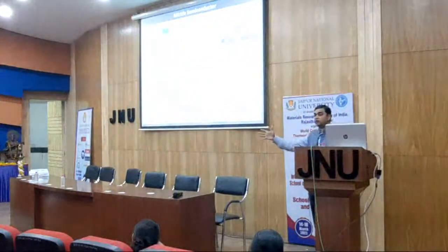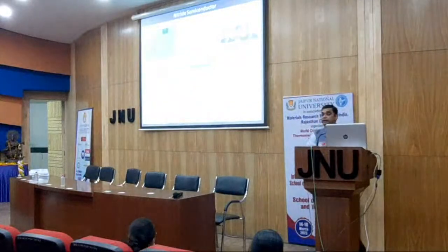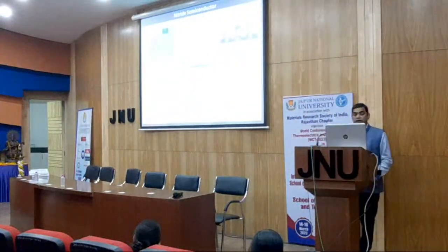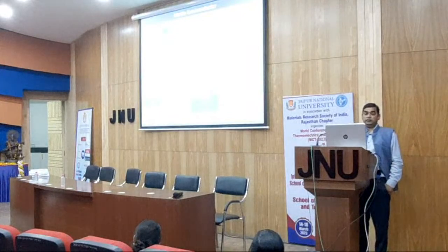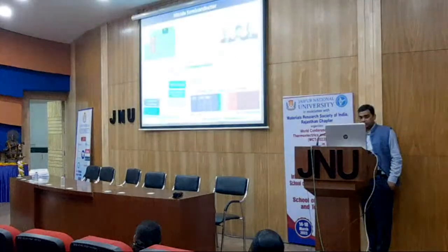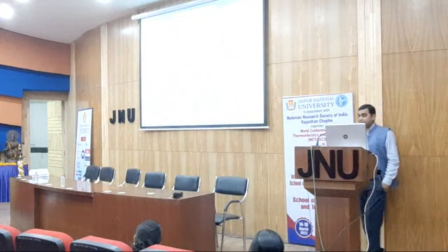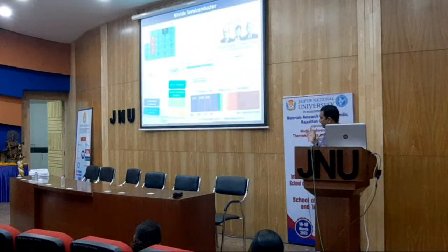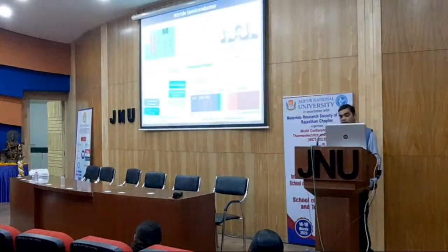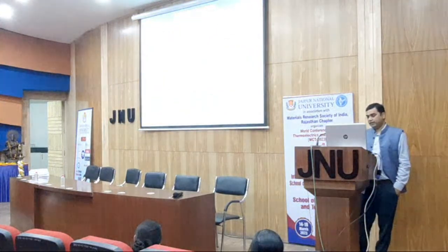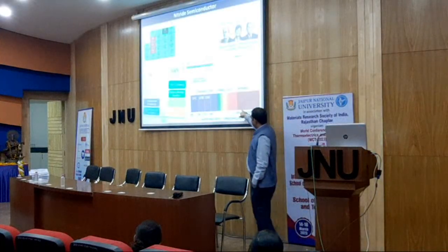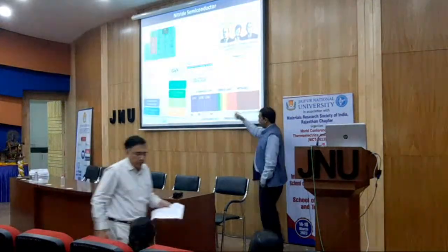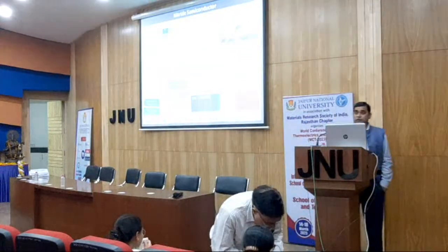If you check carefully, we are talking about 6.2 electron volt to 0.7 electron volt. It means we are talking about the entire spectral range, going from deep UV to far IR. So, depending upon the alloy composition, one can tune the band gap. If you compare with the established silicon technology, high electron mobility is there. But as far as nitride is concerned, in a simple comparison, gallium nitride has a direct band gap, high radiation hardness, excellent temperature tolerance, high absorption coefficient, and if you change the alloy composition, you can cover the entire spectral range. Here, silicon falls only in this line, while nitrides can cover the entire spectral range. And these materials are also fascinating.